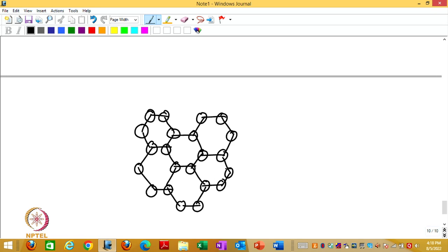Here if I want to figure out the translationally equivalent points, then if I select the center of this atom, then I know that the nearby one was not translationally equivalent. So, I can't select that. I will select the alternate ones. So, the center of all atoms is not forming a lattice, only the center of alternate atoms is forming a lattice in graphene.